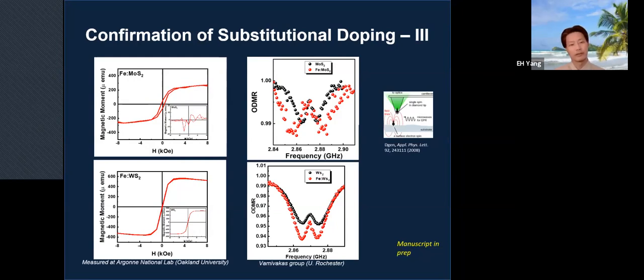So what does this mean? If you pick up any signal from the surroundings, other than the substituted atoms, then these signals would also have to appear in the measurement of tungsten disulfide, because we use a very similar process. We use a nearly identical process, except for some temperatures here and there, right? So we assume the conditions are similar, and we assume you will see similar effects. But as you can see, you see nothing from tungsten disulfide, which ensures that all these measurements come from substituted atoms, right? So this is a double, triple confirmation.